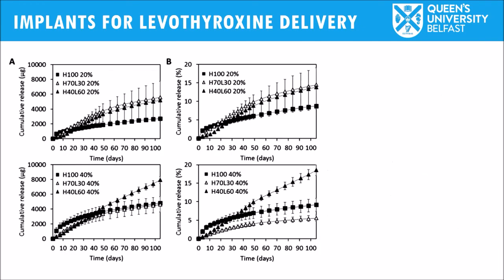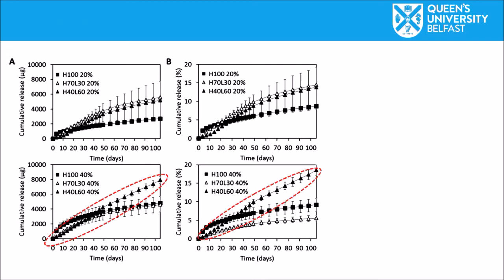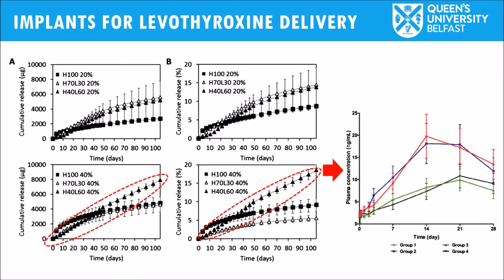Subsequently, we tested drug release profiles of the drug from the different formulations, and it was established that the most appropriate formulation was the one that contains 60% low molecular weight polycaprolactone and 40% high molecular weight, because we have a more sustained delivery for up to 100 days. Obviously, we picked that formulation. We decided to continue using that formulation in an animal experiment, and we used the formulation containing only 100% high molecular weight polycaprolactone as a control.